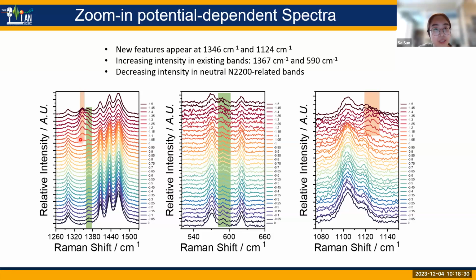So for example, we observed two new features appear. The first one is at 1346. We can see that after negative 1 volt-ish, there is a growth in this peak, and then it continues with a decrease. We also saw a new feature over here at 1124. And similar to what previous literature saw from the IR spectra, we also saw for existing bands that there is an increase in the Raman intensity for both of these two peaks.